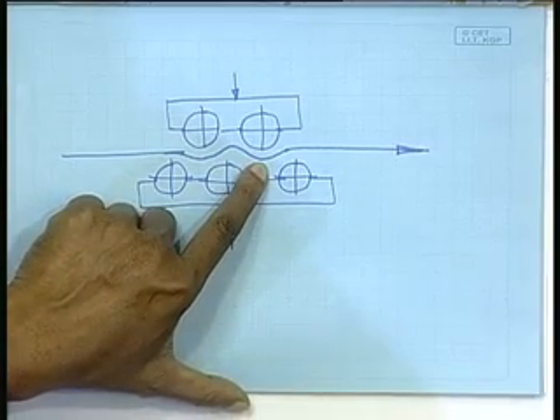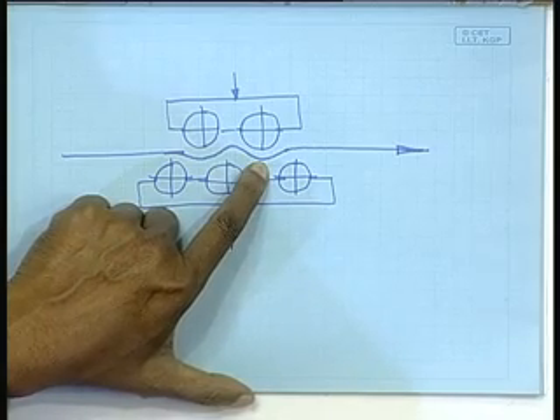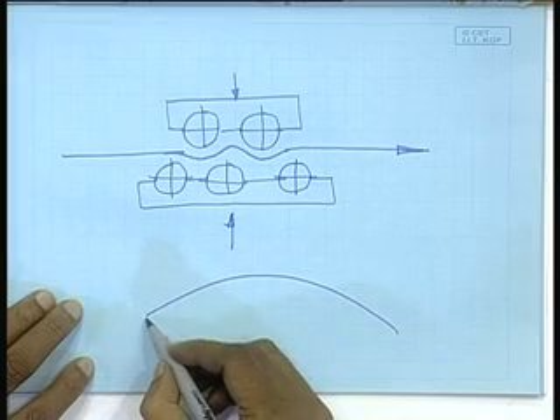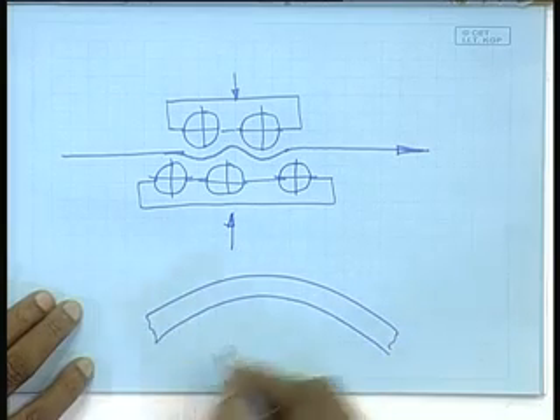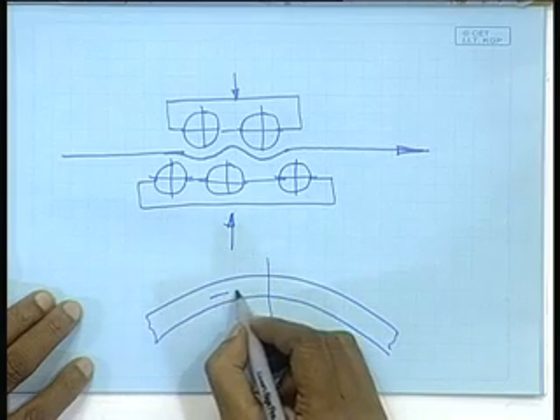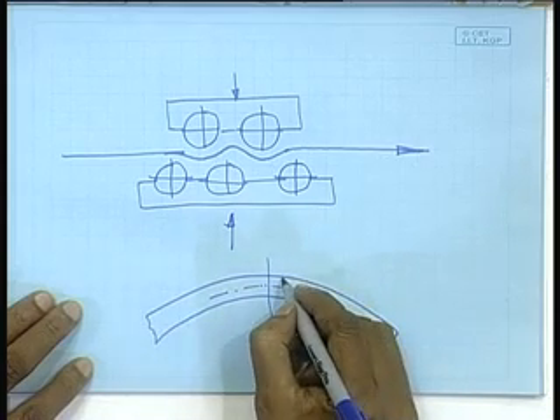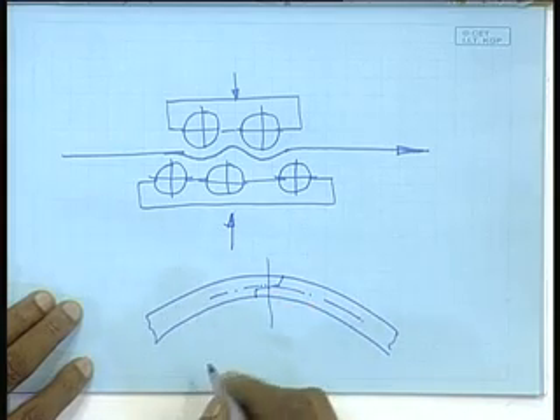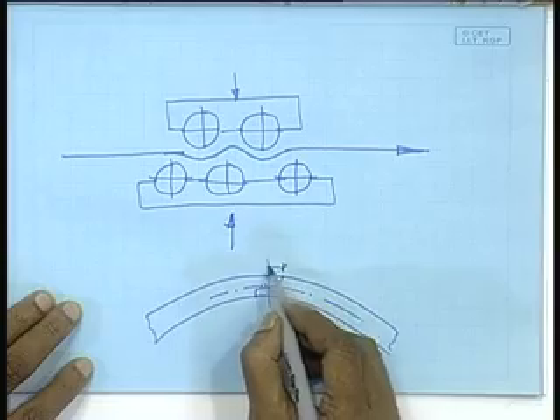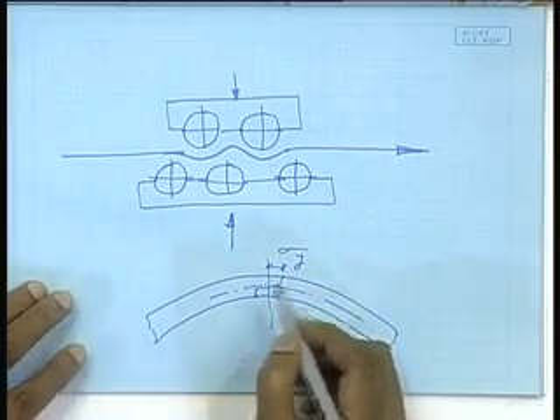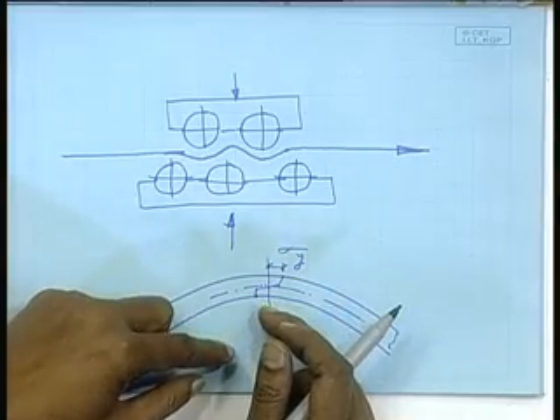So, essentially the plate is being subjected to a stress level much beyond the elastic limit. These are large deformations, meaning the plate is physically getting substantially bent. In the process, in the cross section, if this is your neutral axis, the stress level would look somewhat like this. What does that mean? What I have tried to draw? That means this is my yield point stress. So, almost the entire section has yielded. That means almost along the entire thickness, the top part was in tension, the bottom part in compression. In the next sequence, it just reverses. So, I have given here 3 stress reversals in the process.